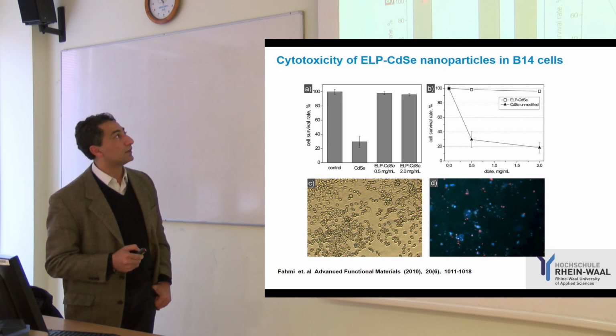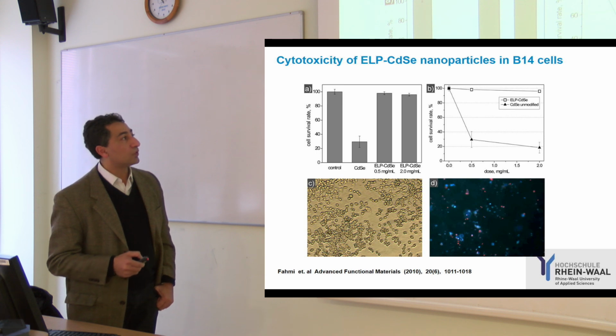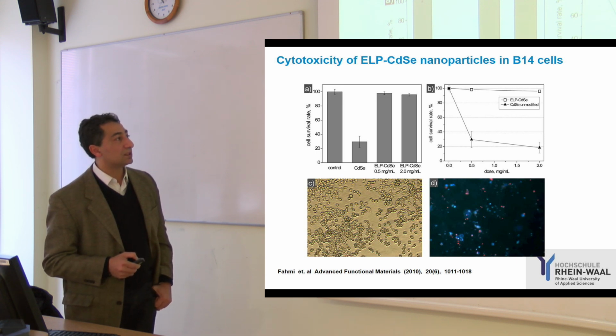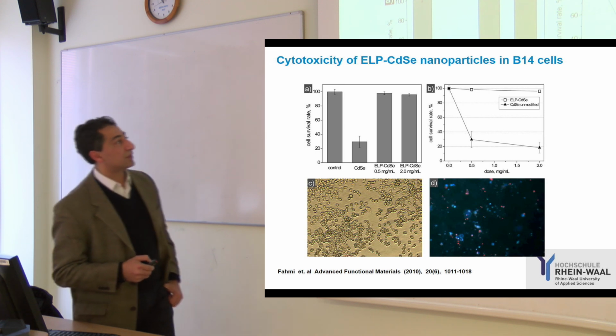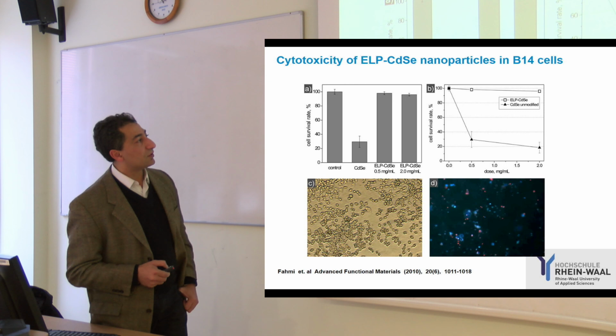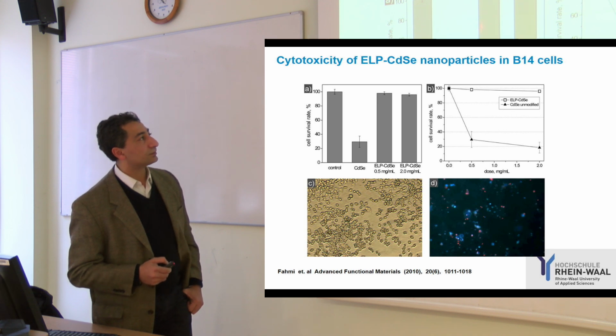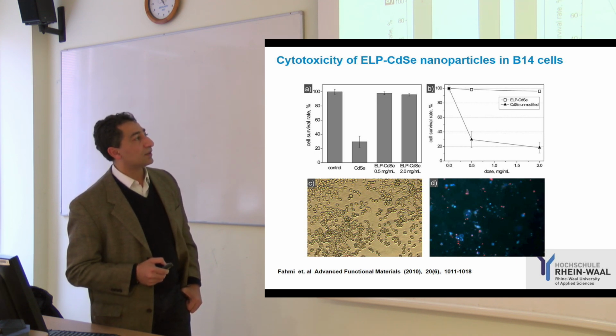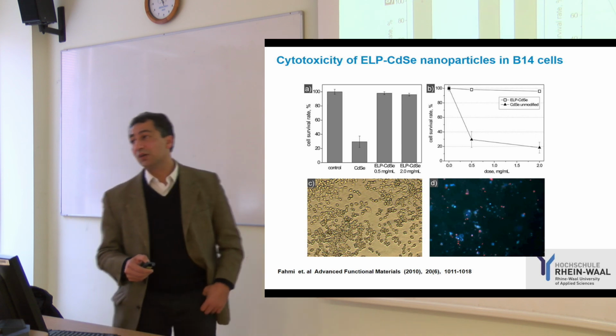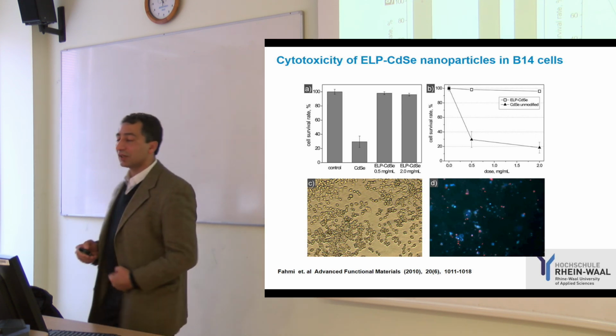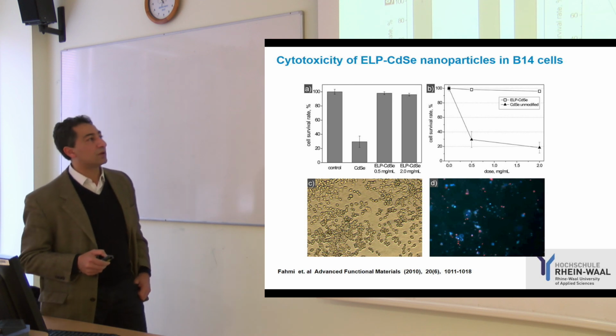This is our control here. In the cell test you can see the cells survive in the control. The material alone, without any coating with this elastin-like polymer, is pretty toxic. Only 25% of the cells survive. Nevertheless, if you coat these semiconductors with this elastin-like polymer, you can see the survival rate is pretty high, so you can really use this kind of highly fluorescent material in a biological system, and you don't worry anymore about the toxicity.